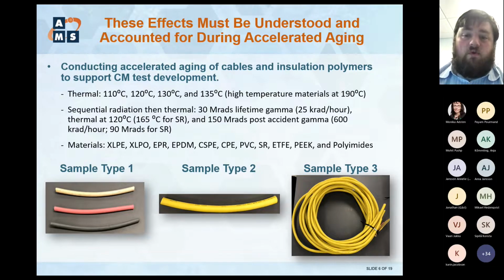And then at different points in that aging process, we're actually taking cables and samples out of the ovens, at different points in the aging of the materials of the cables, and then we send it off and do a LOCA exposure, loss of coolant accident exposure, a design basis event test. In that case, we're subjecting it to 150 megarads of post-accident gamma radiation dose at 600 kilorad per hour, 90 megarads for silicone rubber, and then we're doing a LOCA, basically a pressure temperature profile, essentially. So that's kind of the process we're doing.